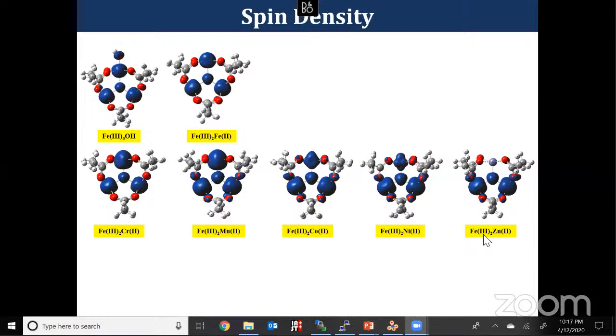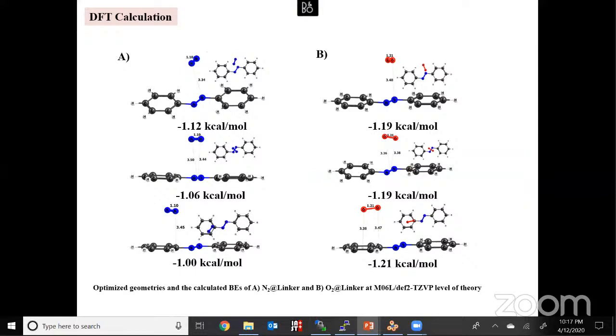We got the spin density graph from quantum chemical calculation. And before calculating the connector part's storage property, we calculated the linker part's adsorption strength for the oxygen molecule as well as the nitrogen molecule. And from the study, we found that oxygen molecules bind a little bit stronger than nitrogen molecules over the linker.